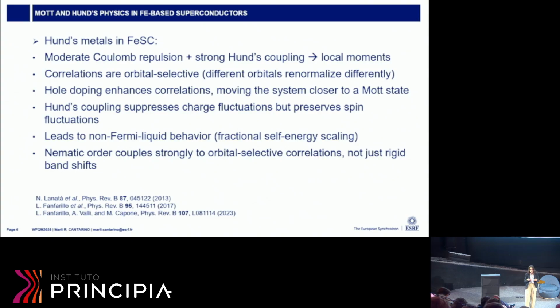And it's expected that when you hole dope these materials, you bring the system closer to a Mott state, so you should be enhancing the localization. We understand this orbital selective physics as different energy scales for the charge screening and the spin screening. This could also bring some insight about the dual nature of itinerant and localized physics in these kinds of materials, and this also correlates with the nematic order.